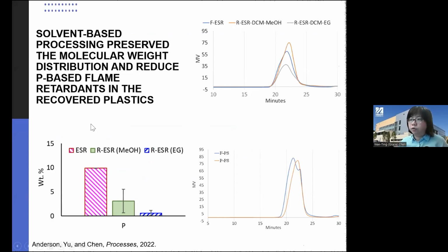So I would like to show you here, we measure the phosphorus content in our feedstock, which is the electronic shredder residue. And we compared the phosphorus removal efficiency when we switch and change the anti-solvent. Phosphorus content here is a key critical element present in these hazardous flame retardants.